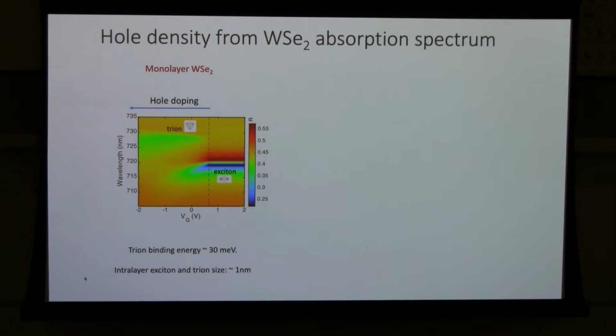In order to do that, I will explain what people actually know quite well about a doped monolayer TMD. How does the optical spectrum change? This shows the optical reflection, which you can think of as an optical absorption spectrum, as a function of the gate voltage, and the vertical axis is the wavelength. On this side, the gate voltage cannot dope carriers into the system. So in this region, the WSe2 is charge neutral.